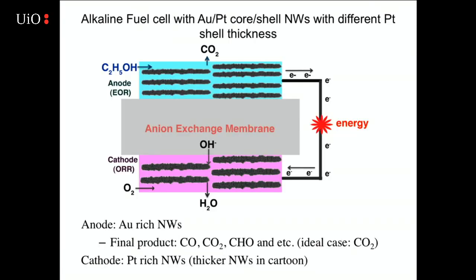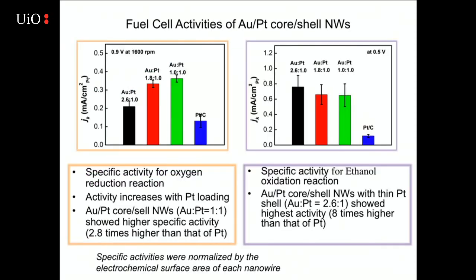And so we wanted to test this for EOR and ORR reactions, so we tested different richnesses of gold versus platinum in different combinations for these fuel cell applications. This is looking at some of the fuel cell activities, and this is for the oxygen reduction reaction here, benchmarking against platinum.